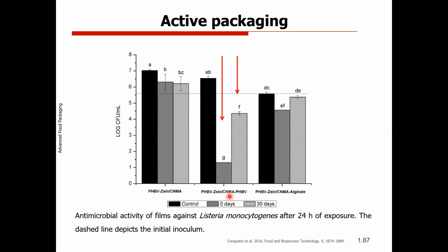This CNMA is the essential oil, cinnamaldehyde, so it's from cinnamon, and we saw that we are able to reduce the growth of Listeria at 24 hours and after 30 days. So it's clear that depending on the structure that you are using, in this case, you are not protecting. In the case of PHBV zein, we believe that this happens because you are not protecting your essential oil with an additional layer, so it is only encapsulated in the zein fibers. But when you put an additional layer like PHBV or alginate, alginate also has some effect, but when you have the additional layer such as PHBV, you are able to protect this release. And it's clear as well that depending on the time, 0 days and 30 days, we decrease the activity. That is quite normal in essential oils because they are volatile and you are losing activity during storage.